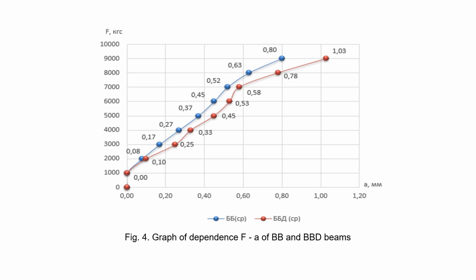At a level of 0.1 to 0.2 of the destructive load, the first normal cracks appeared, and at the destructive load of 0.5 to 0.6, new cracks began to appear. A uniform location of cracks was noted, with a step of 100 to 150 mm, along the length of the beam. Figure 4 shows an almost linear dependence of the increase in the values of the width of normal cracks with increasing load, which is typical for beams with composite reinforcement due to the lack of yield properties of the latter.